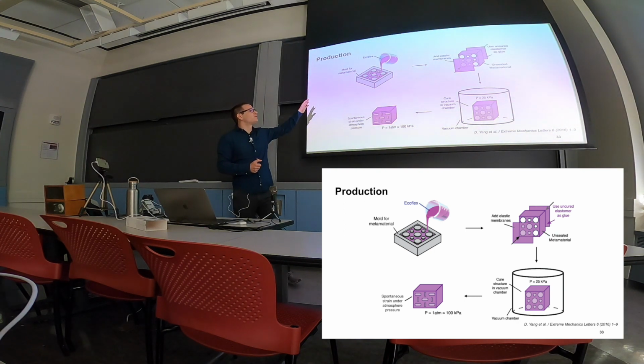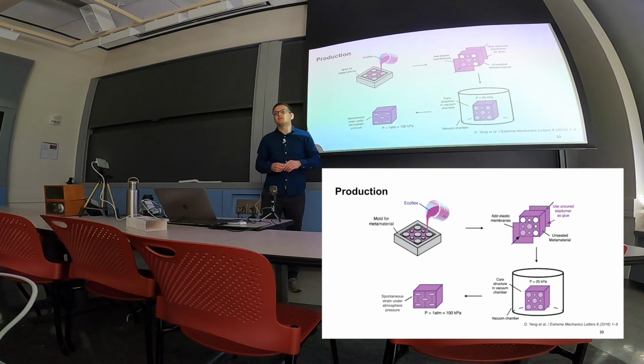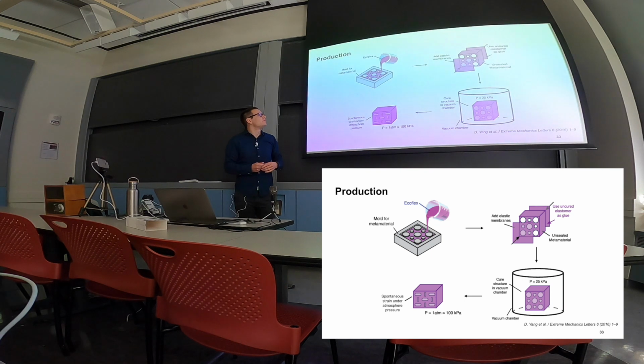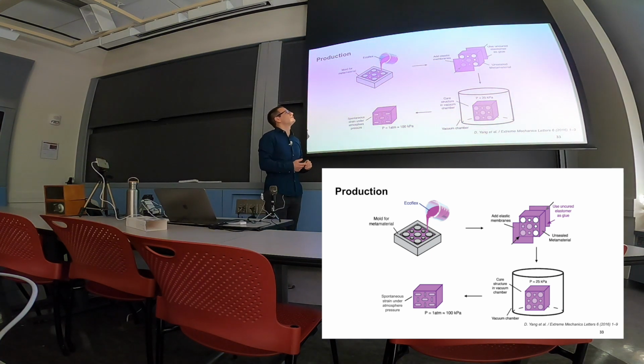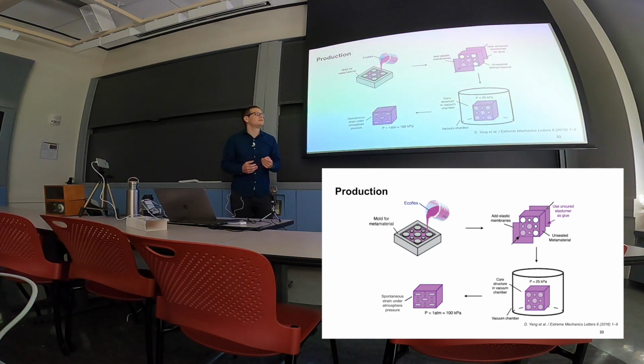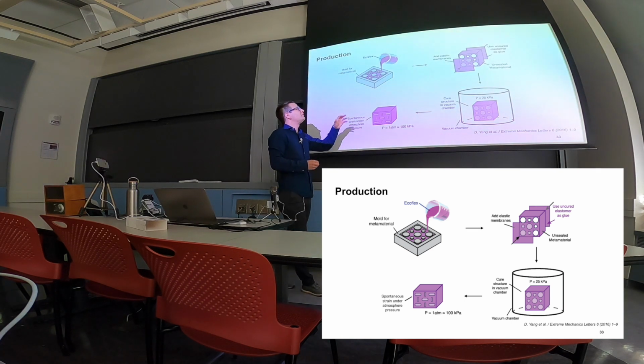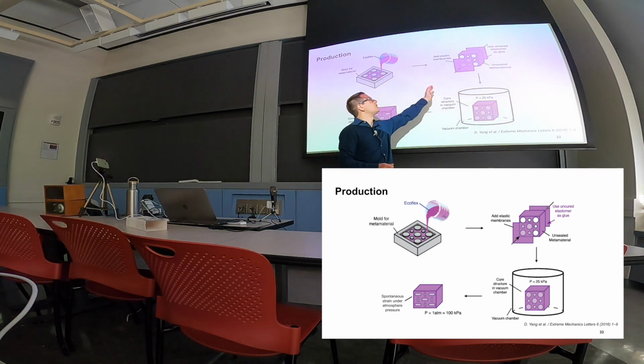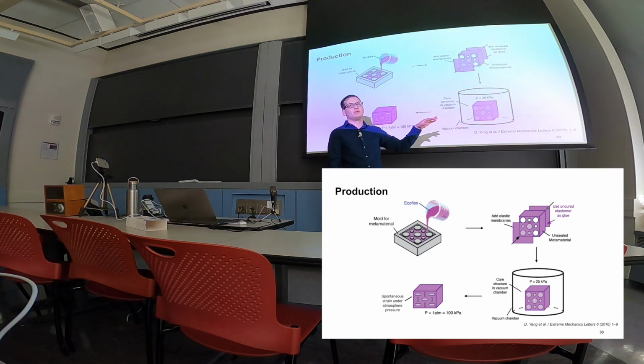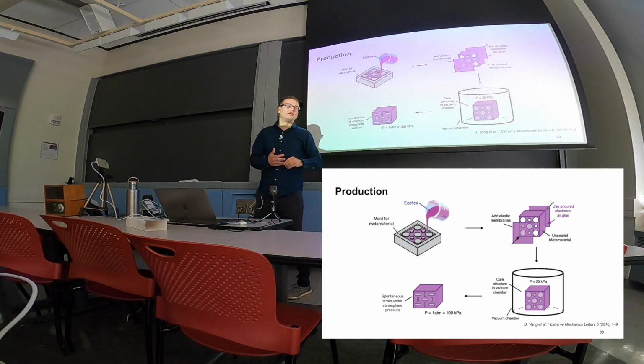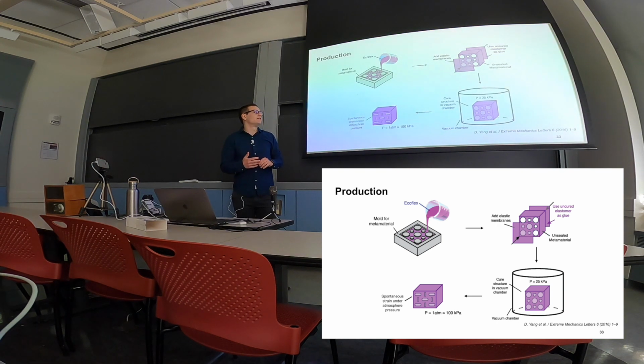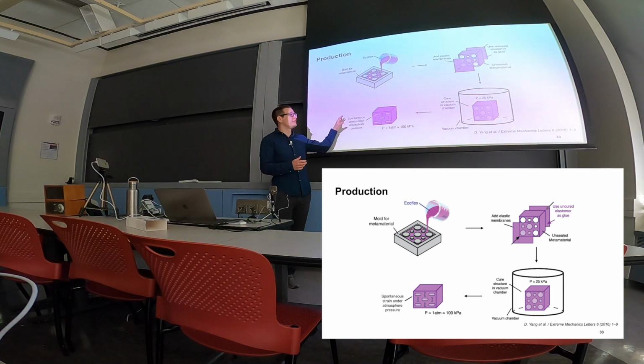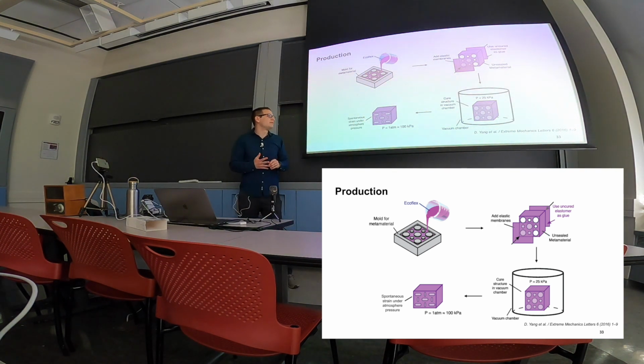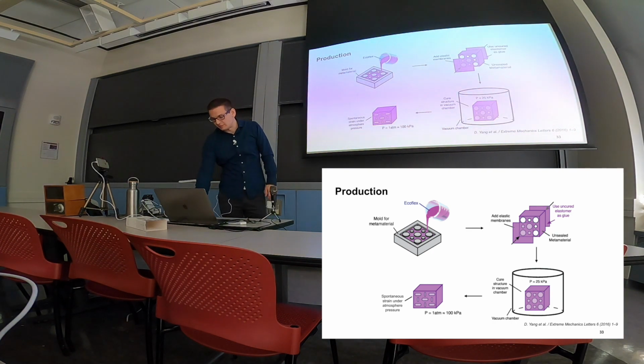So what we need for producing that material is once again the negative mold of that metamaterial, then filling it up once again with the soft material like Ecoflex, the same that I just used before, letting it cure inside of the mold, and then attaching a top and a backing layer, which is still uncured, and letting it cure inside of a vacuum chamber, so that there will be vacuum inside of those cells while curing. And then once it is cured, we can just remove it from the vacuum chamber and it will spontaneously snap into one of the stable states. And then we can use it as a metamaterial.